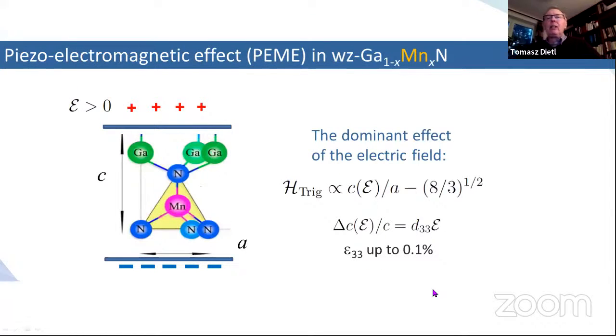And actually, we know that this trigonal anisotropy, this trigonal Hamiltonian and the related anisotropy, depend on the ratio of C-axis to A-axis, and minus something here. Why? Because if the C to A is equal to the square root of 8/3, we have a regular tetrahedron, and all surfaces are identical. But if we apply the electric field, we can change this ratio.